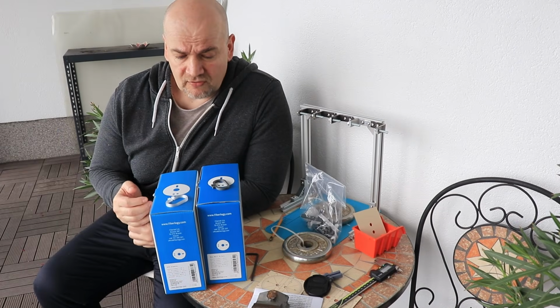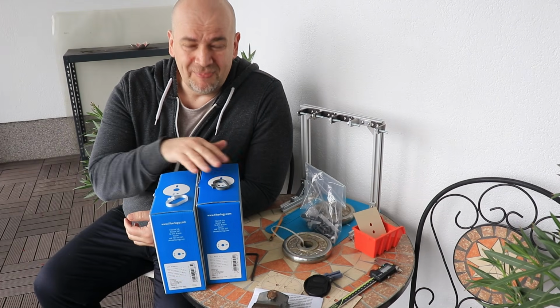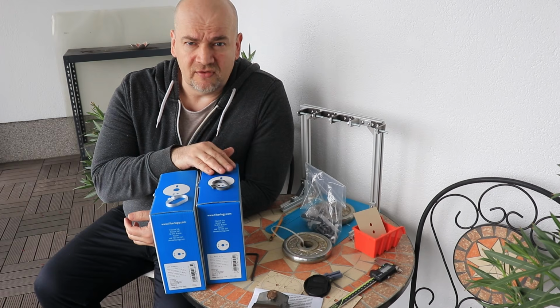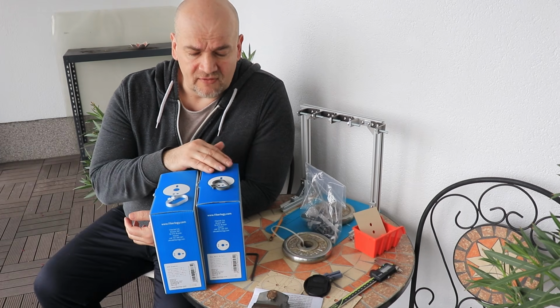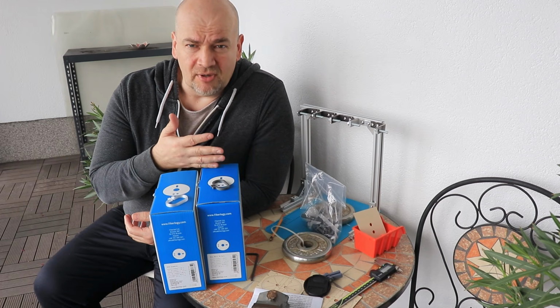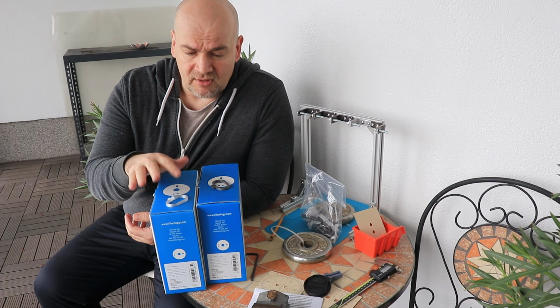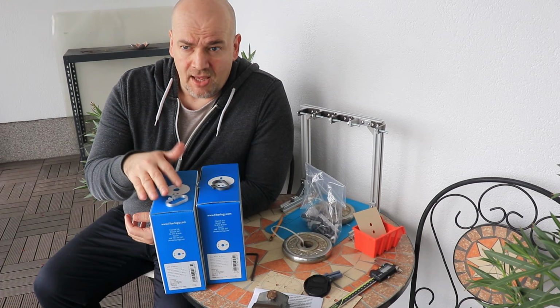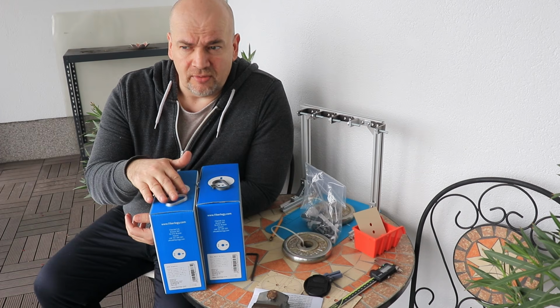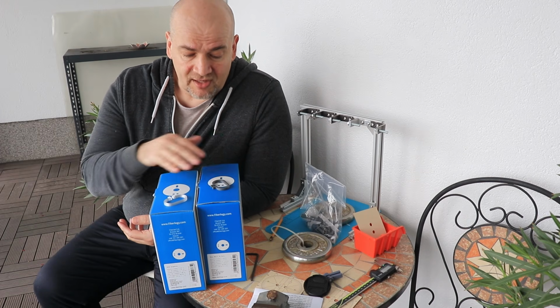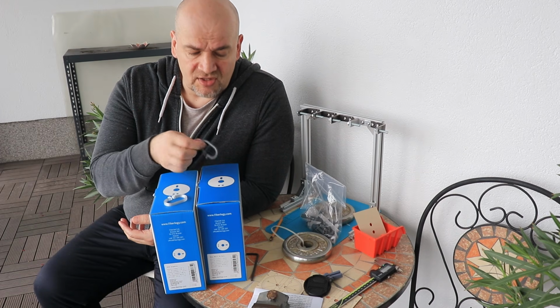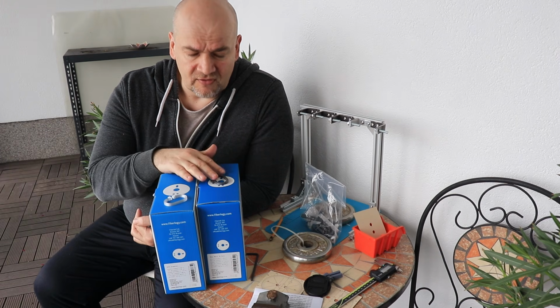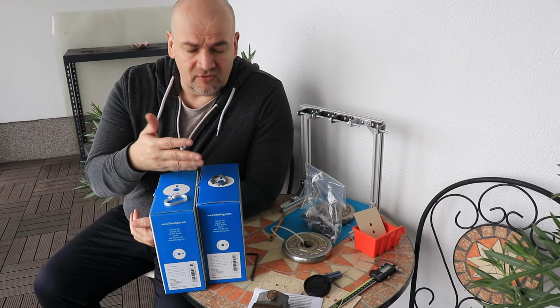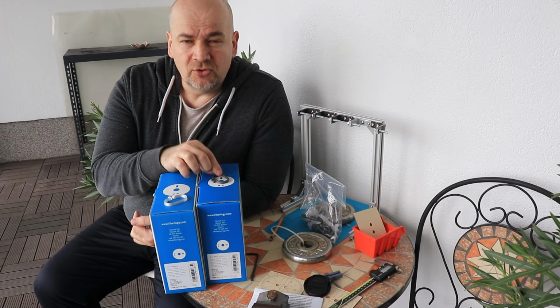And now the conclusions. Well, partly I can confirm that the PCTG has a better thermal resistance and is stronger in impact test, but the difference is very minimal. In all other experiments the PETG is better, and don't forget it is much cheaper. The only reason I can see to use the PCTG is that you really need those few degrees of Celsius of thermal resistance, or maybe those 15% of the impact strength, and you don't want to print inside